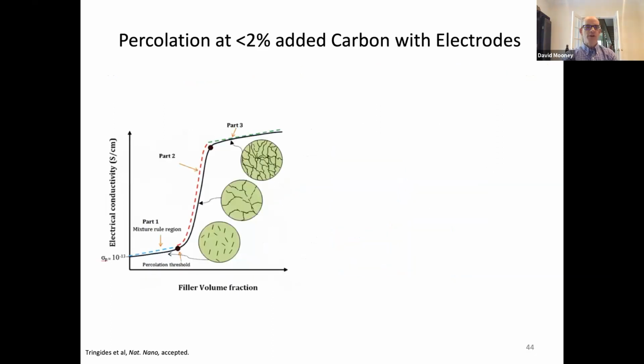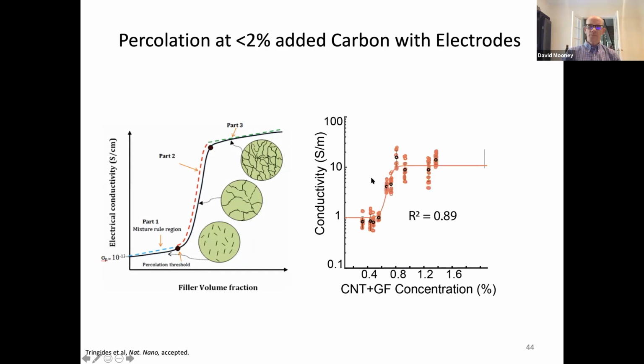So those of you who are familiar with percolation theory, the basic idea is that the electrical conductivity, if we have electrically conductive particles, presumably will be quite low when they're present at a low volume fraction, but as they start to interconnect, the conductivity should go up significantly. And what we find is we can get very good conductivity in these materials once we get above about 2% added carbon material. So we get a good percolation at a low enough carbon content that we don't significantly change the mechanical properties of these alginate hydrogels.